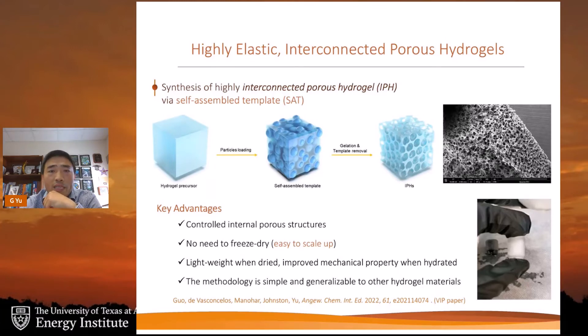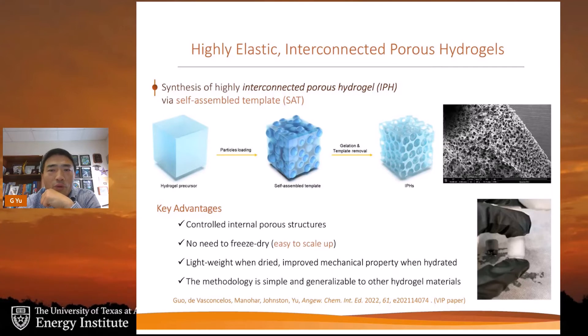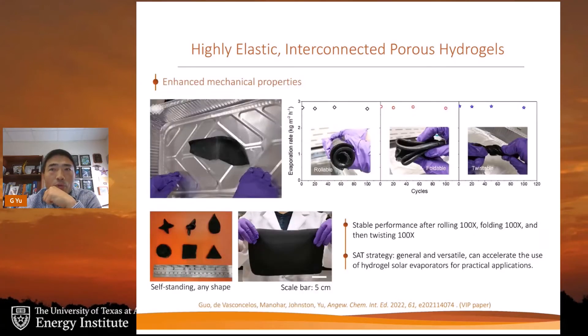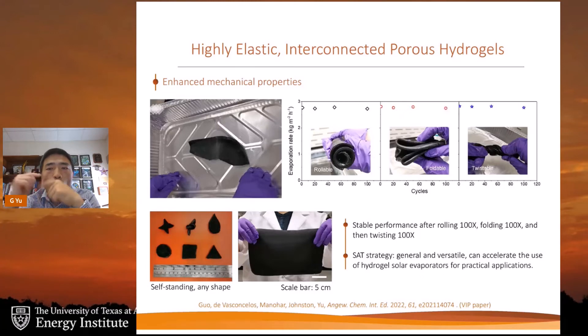We can control the internal porosity without the need for freeze-drying, which is typically required to maintain the micro- and nanostructure of hydrogels. The resulting material is extremely lightweight and mechanically very stable. As shown in this slide, our newly developed hydrogel remains workable even after various rolling, folding, and twisting over a hundred times, with stable performance. This technique is versatile and general, and we believe it will accelerate practical applications of our hydrogel.